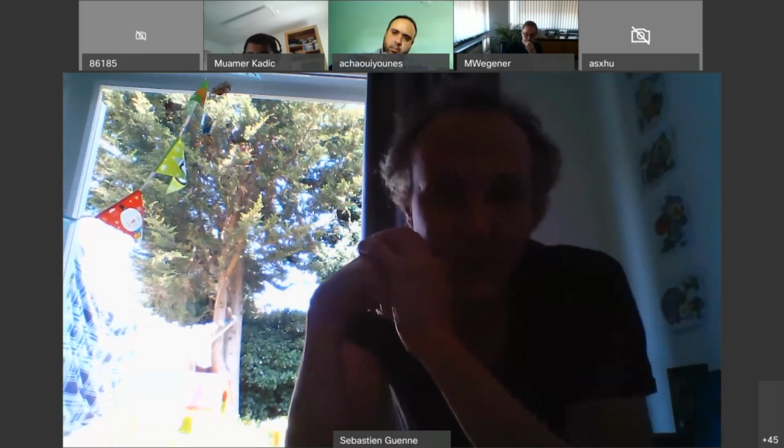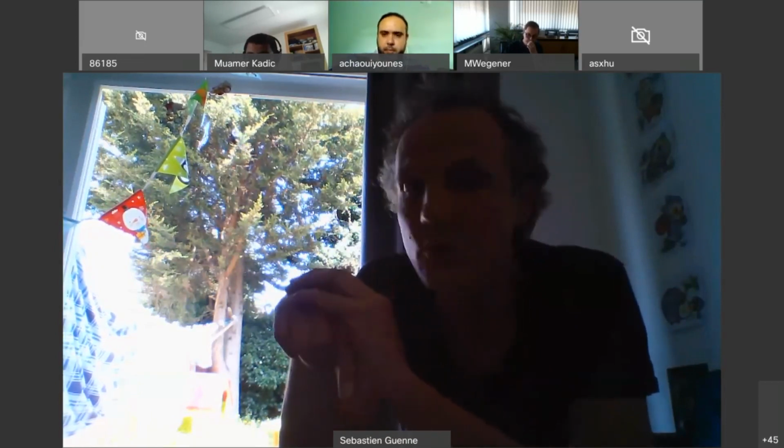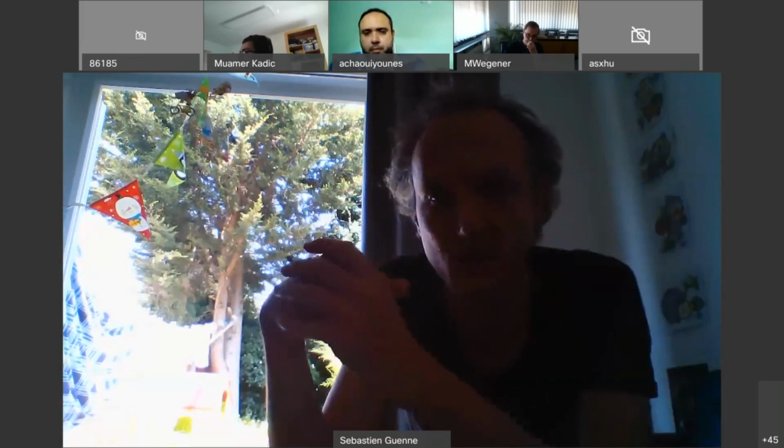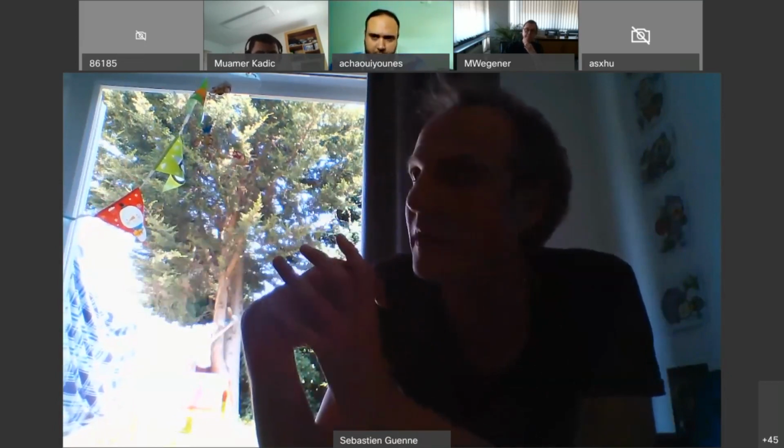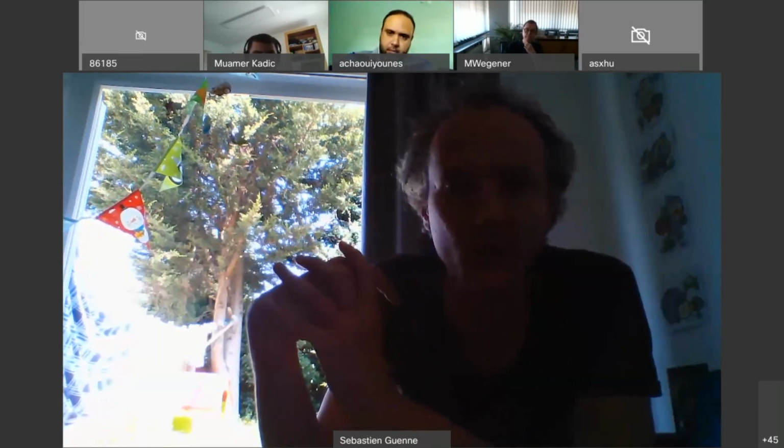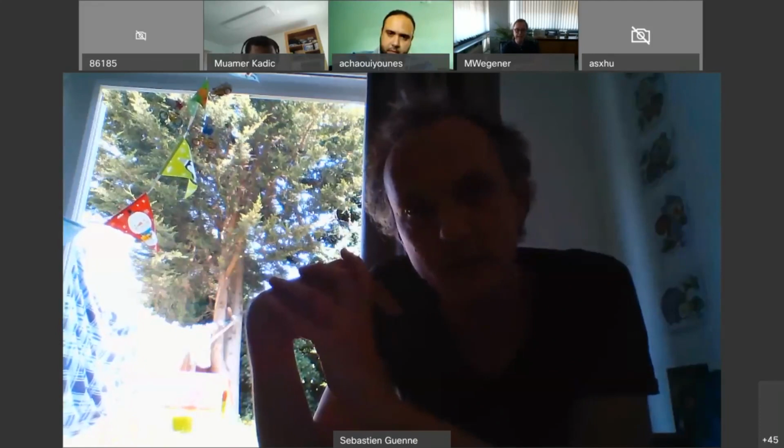Okay, I've got a question anyway. So you have the new chiral metamaterial structure, which has these additional bars now. And how does it compare to the previous one in terms of anisotropy? Is it more isotropic actually than the previous one? No, it's more anisotropic. I didn't mention this. The original one had cubic symmetry, whereas the new one has tetragonal symmetry.